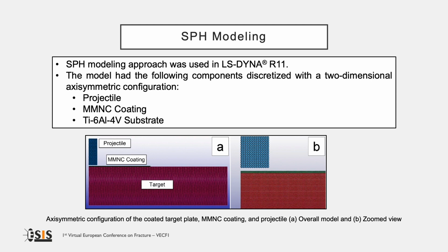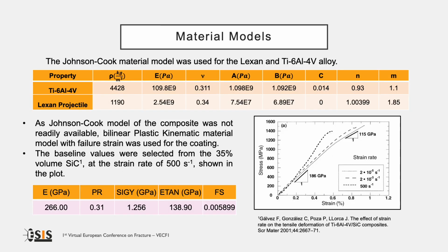No boundary conditions were applied to the edges of the target, since it is a hypervelocity impact and the results are not dependent on the condition far from the impact region. Three different models were developed with different particle spacing. The final choice was the one which is displayed on the figure on the right, which had better accuracy in the prediction of the experimental results. The Johnson-Cook material model was used for the simulation of the material response of the Lexan projectile and the titanium 6-4 substrate.